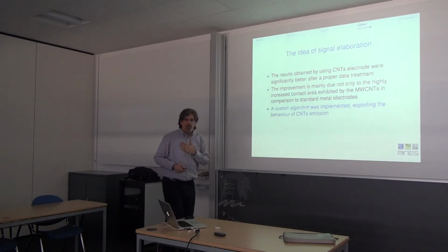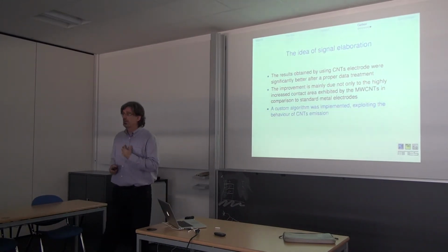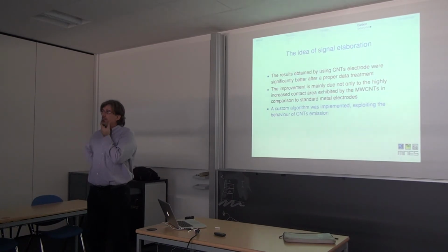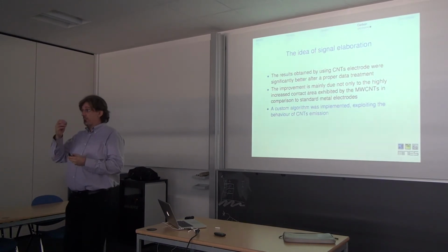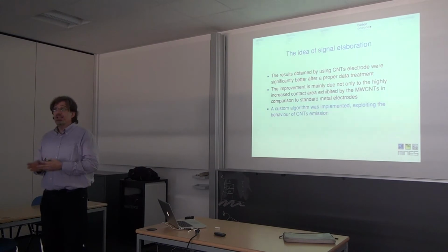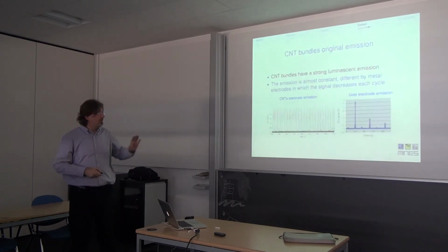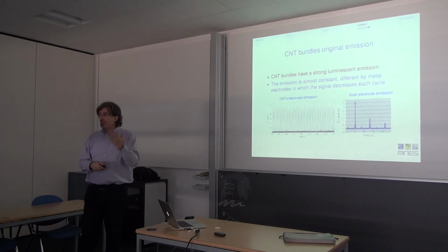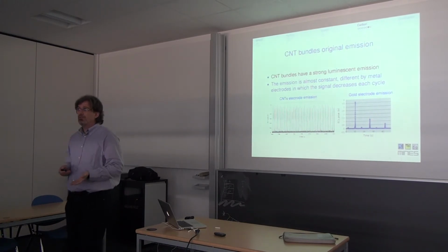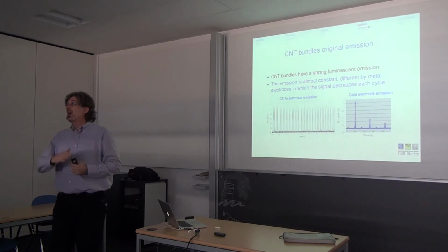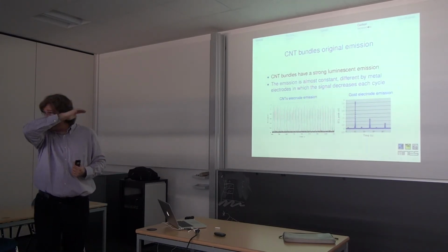So we are arriving from an electric. Yes, please. So in this case, why with gold electrodes does the signal decrease? Because of the property of the material. So it's a kind of oxidation. Surely there is oxidation, there is polarization of electrons, and in this case electrochemists have a lot of information on metals, and it is normal. It is what you expect. You lose in efficiency. With carbon, you don't have this loss. You have it, but the time constant is much longer.